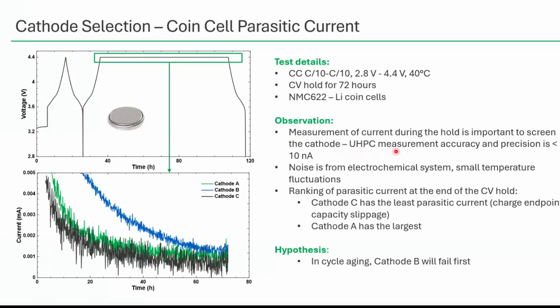Our UHPC measurement accuracy and precision is less than 10 nanoamps, and here I'm looking at hundreds of microamps. Any noise we're seeing is actually electrochemical system level noise, maybe small fluctuations in temperature. So all of this is real measurements occurring, and we can take this measurement directly and start to make conclusions about the electrochemical stability of these cells.